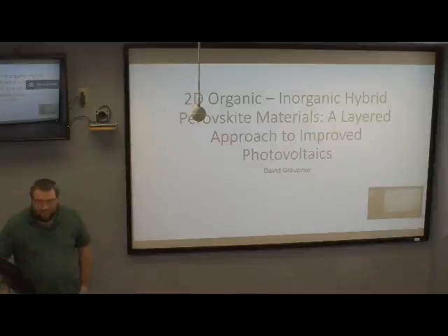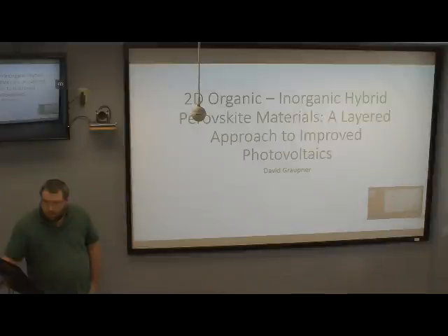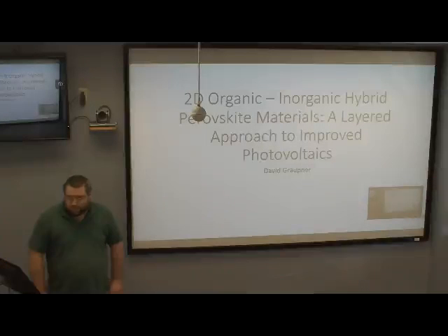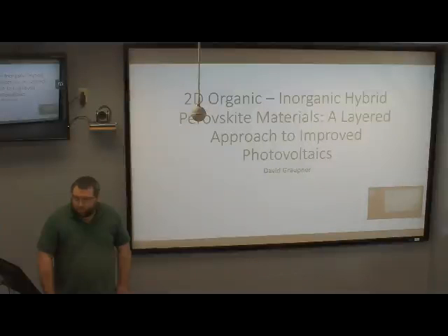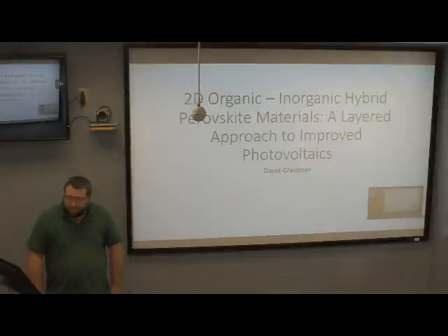Title is okay. Yeah. So what is bad about perovskites? What is their main weakness and challenge? The environmental stability. And for simple guys, what does it mean? They decompose due to moisture, light, heat, and oxygen. And so they decompose when they interface with stuff. So you need to seal them. Okay. And are there any advances to solve this problem if you do a layered structure?